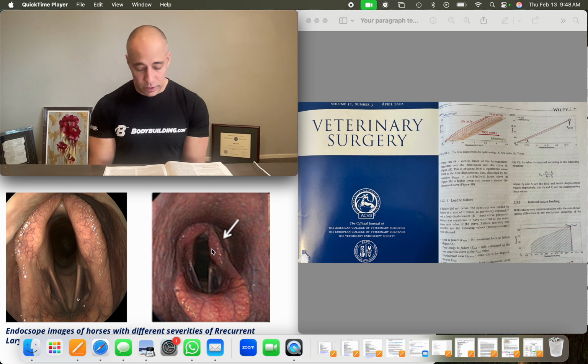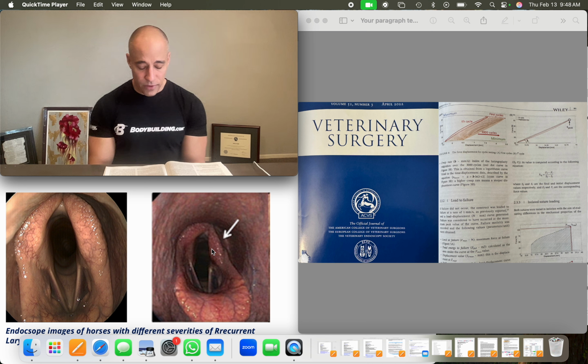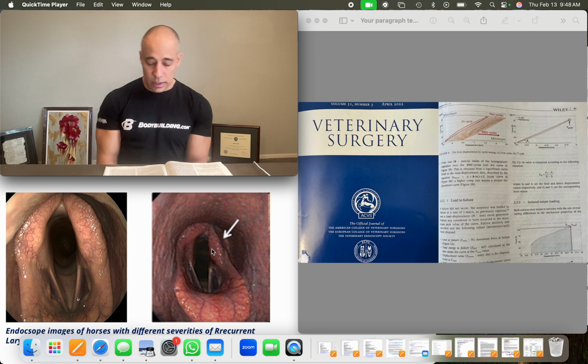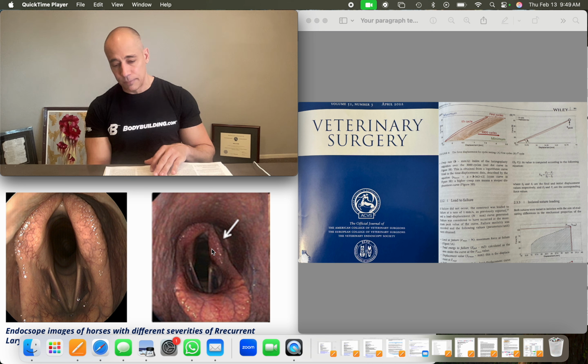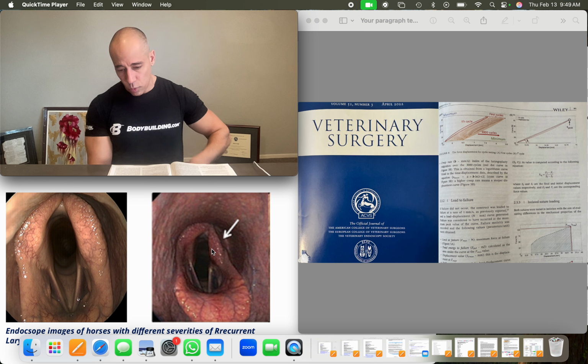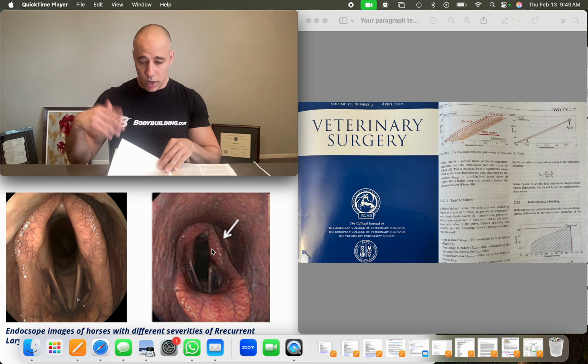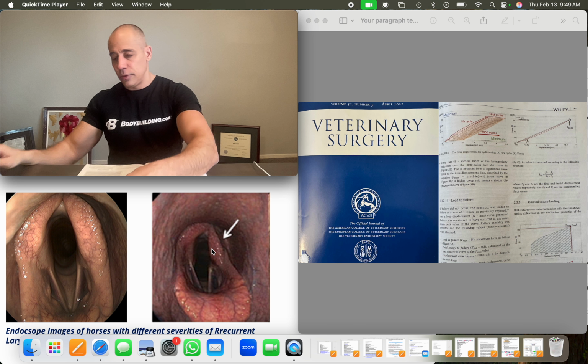A study reported a failure of the arytenoid cartilage at 240 and 142 newtons for Ethibond and fiber wire sutures respectively. Similarly, in another study, arytenoids anchored with a self-tapping cannula connected to fiber wire failed at around 180 newtons, and then another study by that same group revealed higher values for Ethibond at 280 newtons and fiber tape at 220 to 340 newtons, depending on the construct. The swallowing frequency of horses recorded in vivo is 0.013 hertz, which is what causes a lot of the pressure, they think, to the surgery, risking its failure in real horses.